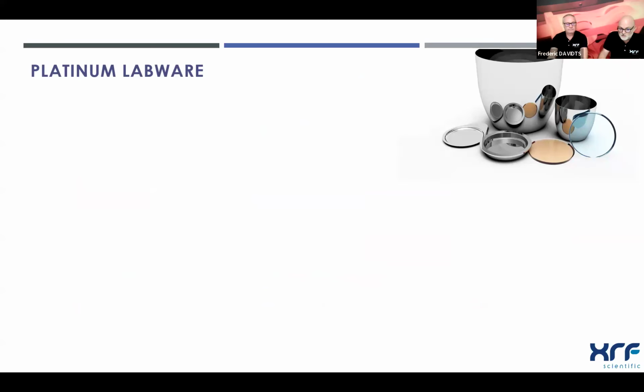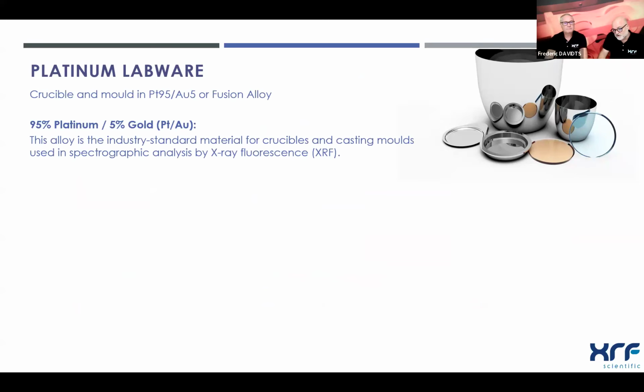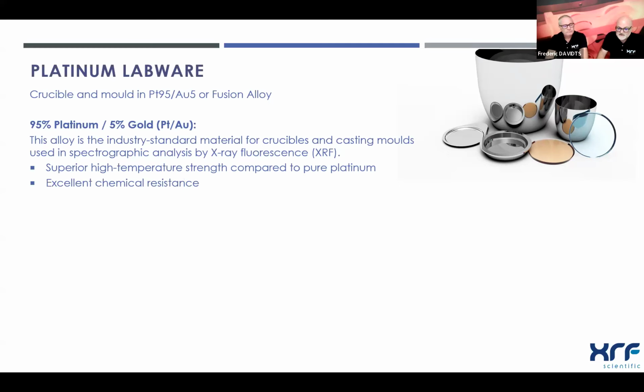The platinum labware is also really important, and for the XRF fusion, we are using a platinum-gold alloy. The first reason is that it's far more strong compared to pure platinum. We have an excellent chemical resistance. Of course, if the elements are metallic, you need to oxidize them, but nevertheless, you have good resistance. And also the fact that we have 5% gold gives a non-wetting property to this alloy, and of course it's very good to release the beads easily from the molds.